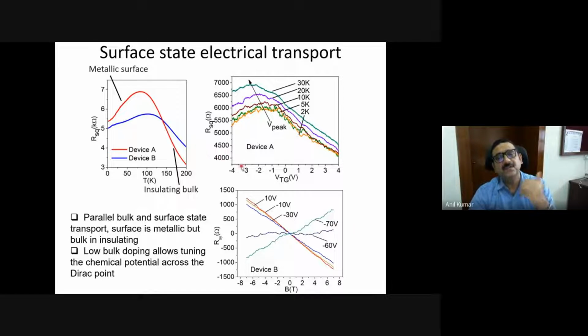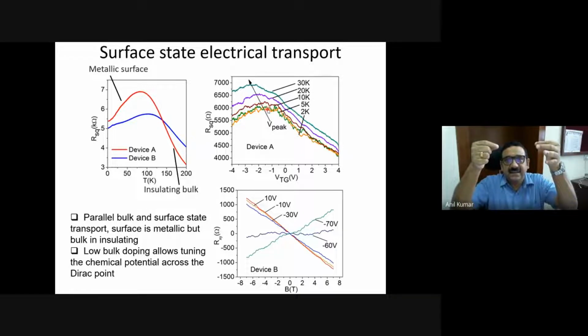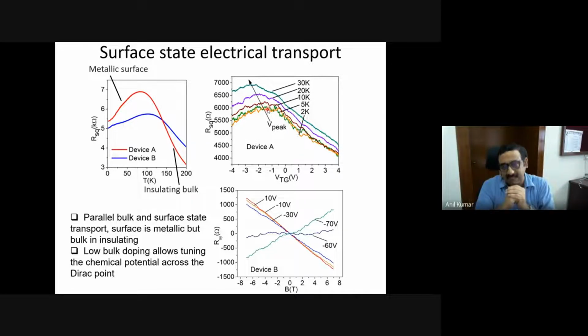So then what we do, we go to the next measurement where we start changing the gate voltage. You apply a voltage to the top gate and you start changing it. Keeping the temperature of the crystal at 2 Kelvin, you see that the resistance keeps on increasing. It reaches a maximum and then starts coming down. Why it is going through a maximum is that, as I told you initially, there is something called a Dirac cone, and the center of the Dirac cone is a charge neutrality point. If the Fermi level is above this Dirac cone, it is an N-type conducting material, and if the Fermi level is below this Dirac cone, it becomes a P-type conducting material.